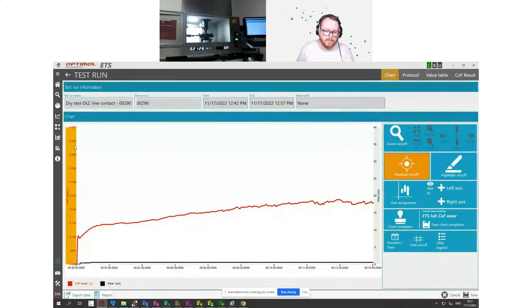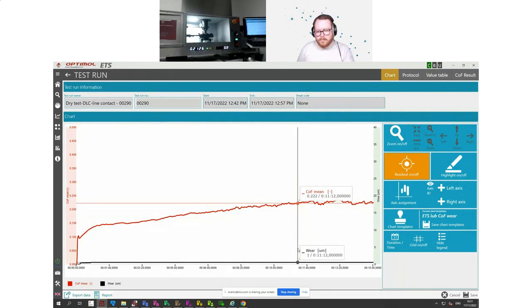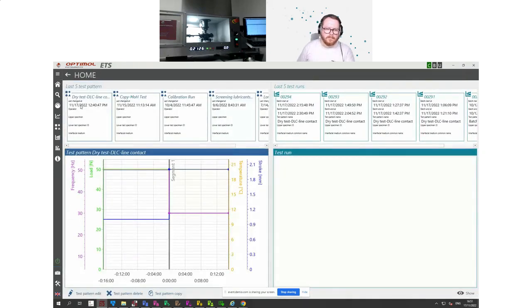And you can see here in red, we represent the coefficient of friction. The tests were run under dry conditions. The coefficient of friction is about 0.2, 0.21, while the wear remains very low and doesn't increase over 1 micrometer in depth. In parallel, we are now starting the test with another sample.